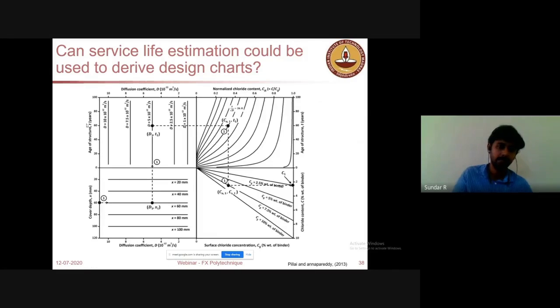I think in reinforced concrete design, there are some design charts for designing columns and beams. Similar to that, which is strength-based design, if you want to have a structure for 40 or 50 or 60 years, you should be able to choose the diffusion coefficient your concrete will require to achieve the necessary service life. Then you calculate how much chloride content would be expected at a period of time based upon the location of the structure, and similarly choose how much cover depth is necessary. For example, for a chloride content of almost 2.5, you may need a diffusion coefficient of 5 into 10 to the power minus 12, and to achieve that diffusion coefficient as well as extend the service life, you should have a cover depth of 60 mm.